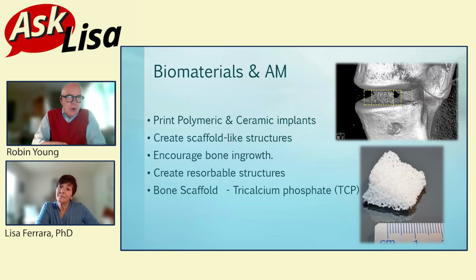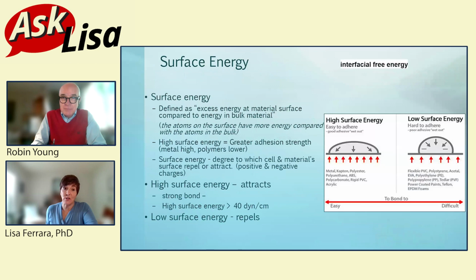Absolutely. So, one of our questions that came in was, how would you quantify the benefits of these various 3D printed textures in terms of surface energy? Now that's an insider kind of question, but it's interesting. And I've looked at the surface energy, and for our audience, just to explain it at a real high level, it's the excess energy at a material surface. And it's related to cell adhesion. The higher your surface energy, it attracts the cells. You get better adhesion, you get a stronger bond, versus low surface energy where it repels.